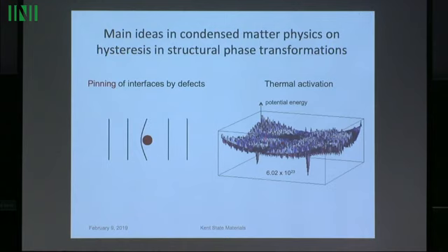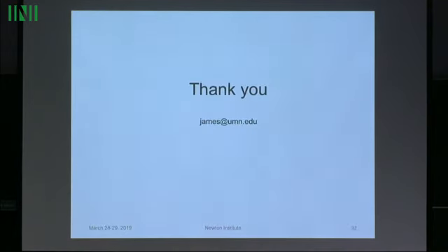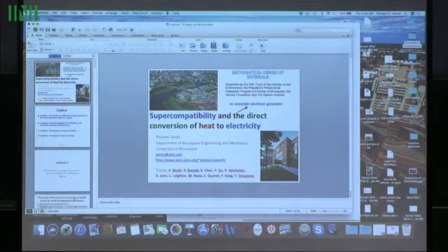But as you can easily imagine from this picture, it might be much more difficult for the system to find its way back into this energy well than it is to get out of the energy well in the first place. And that could give rise to hysteresis. That's like thermally activated mechanisms for hysteresis. So both of these are very different ideas, and either one could be relevant, but actually I'm going to tell you a third idea we feel is even more relevant. Oh, okay, that was the end of the first lecture.